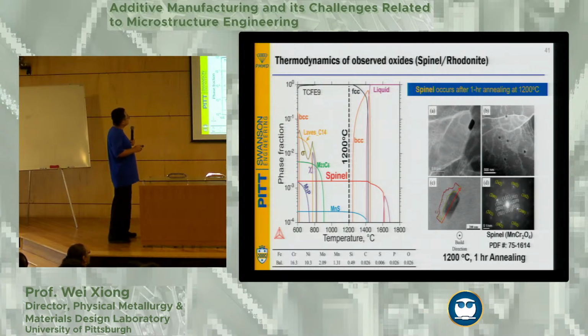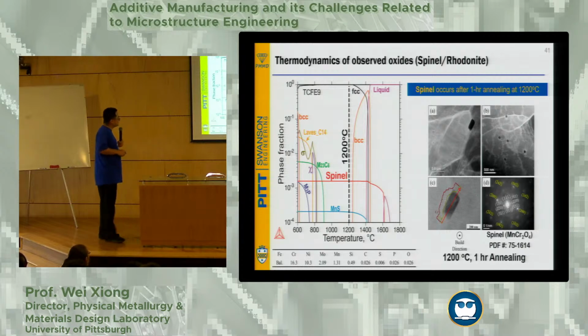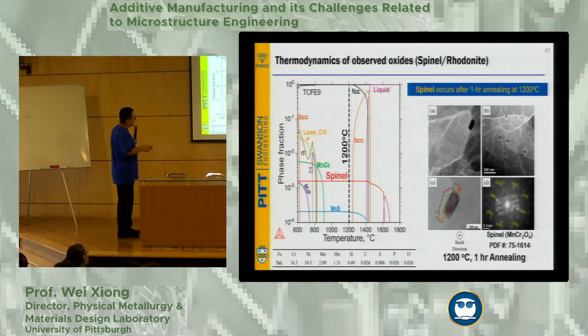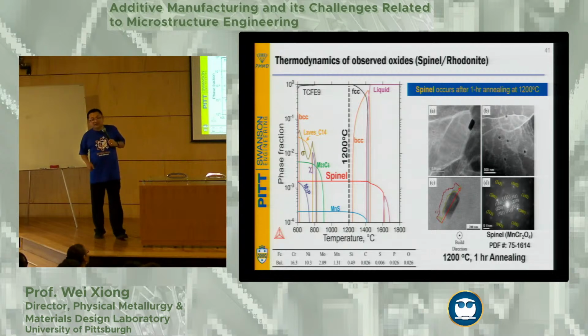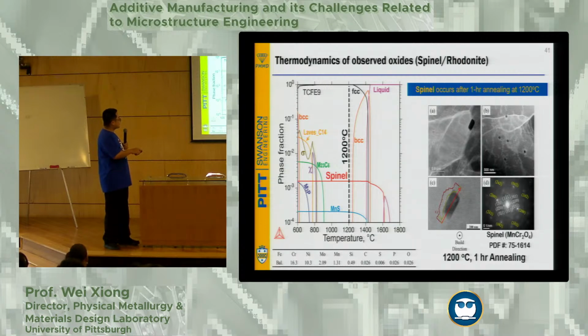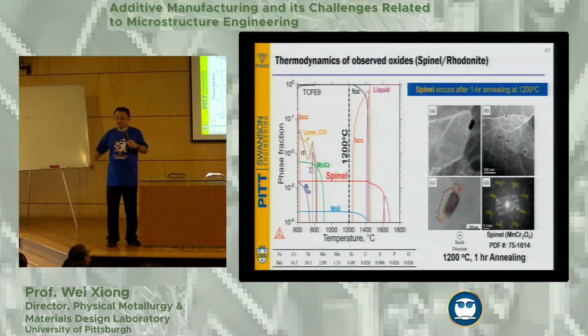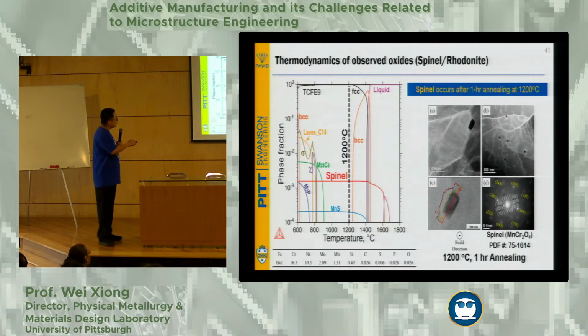If you do the calculation, you see, I put the composition, using the iron database, including the oxygen content, and you can see the spinel phase is actually showing up. This is perfectly the ideal size and fraction of the spinel particle. In addition, the fraction has to be low. If you have too much of the spinel particle, that will become an inclusion later, so you really want to get this very low fraction of the spinel.